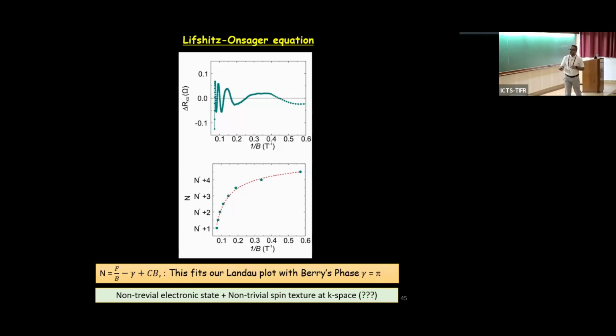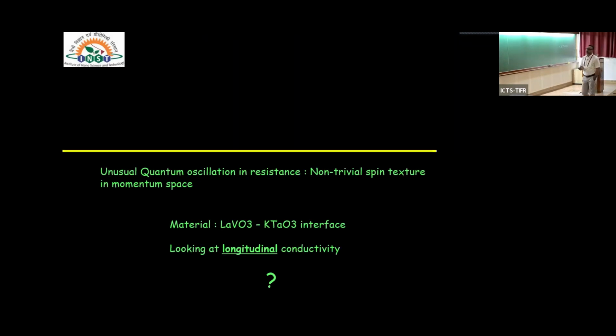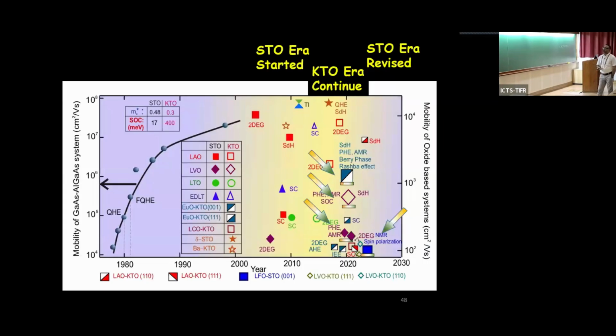One, we have seen the appearance of a derivative of the susceptibility term in the system, and we have a non-trivial electronic band structure. So from this, what we are concluding is the unusual quantum oscillation in the resistance, non-trivial spin texture in momentum space possibly, and where it is reflected, in contrast to a topological Hall effect, it is reflected in a longitudinal resistivity.